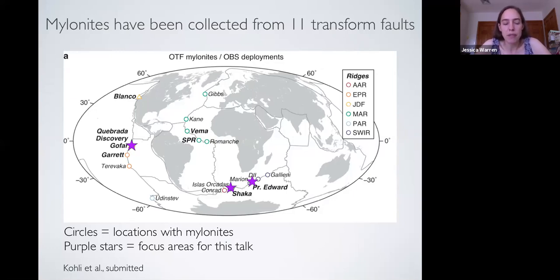And so the limiting factor in terms of thinking about this is that there is a sampling bias, because in almost all cases, the dredging that's been done is not dredging with a focus on sampling the transform fault zone and getting at the deformation. It's dredging that was done to look at often just the deeper lithospheric portion that's exposed in the transform fault wall. And so the dredging hasn't been focused on deformation, it's been focused on getting deeper lithologies. So we don't have sampling that really reflects what is probably down there in terms of the fault exposures. We just happen to have kind of lucky finds when the dredge hit the fault zone.